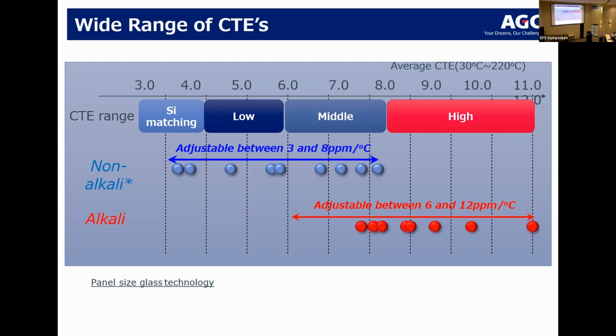We call it non-alkali, but there's a small percentage of alkali for forming glass. It's about 2 to 3%. The alkali containing glasses are around 20 to 40%. So they really attenuate the signal. Attenuation is caused by the electron clouds in glass. As the signal goes through the glass, it gets absorbed and desorbed by the electron clouds in the glass.